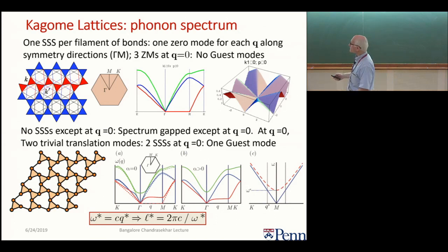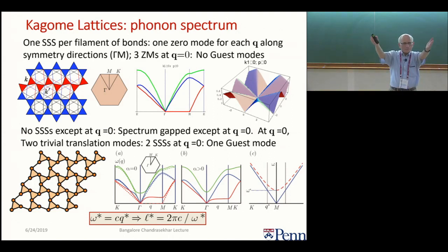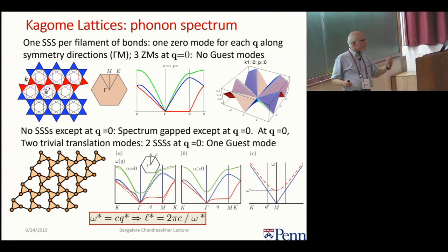And indeed, if you go and calculate the spectrum of phonons, this is what it is. If I go along the line gamma to M, I have a zero mode for every wave number that goes from gamma to M and in the two complementary directions. Here's what the lowest modes look like. This is the frequency, and this is qx and qy, and you have these knife edges coming down, straight lines coming up, and zeros everywhere. Now what happens if I add a next nearest neighbor bond? Then I'm adding extra constraints, and the Maxwell theorem, or the Calladine theorem, takes a different form, and I no longer have zero modes. So this gets lifted up, and it looks like this. It gaps the spectrum completely.